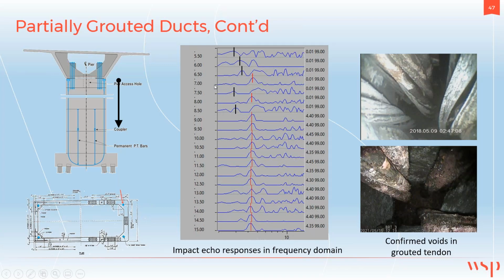Here in the middle, you see the frequency spectrums, which are from about 5 foot to 15 foot measured from the top. Now, if we look up here, we see that the peak frequencies are all over the place. And you can see the shifted frequency, which would be these black lines. The black lines show the shifted frequency.